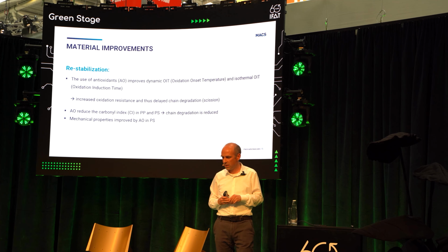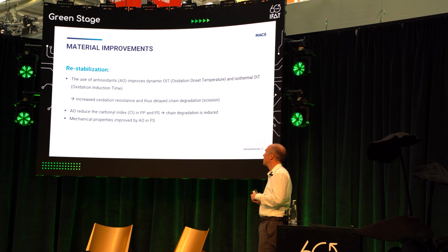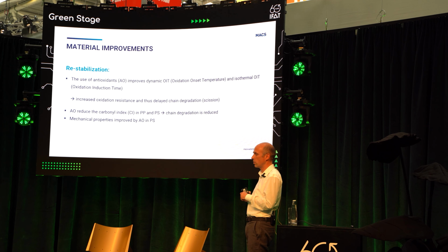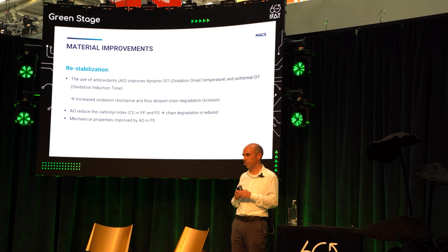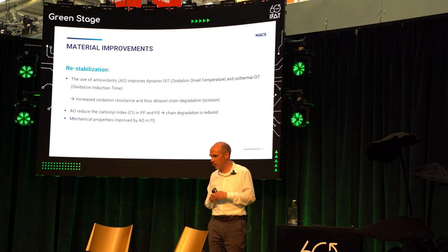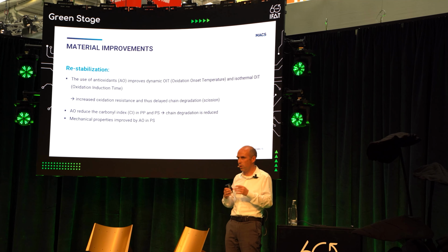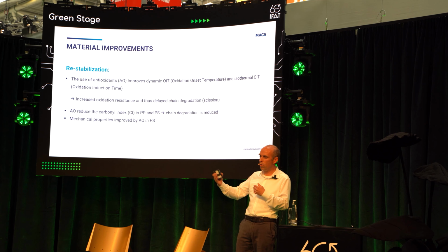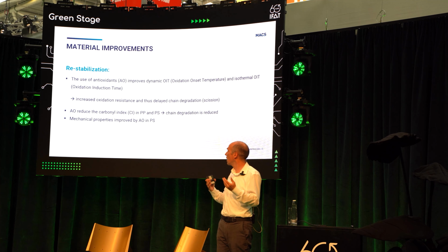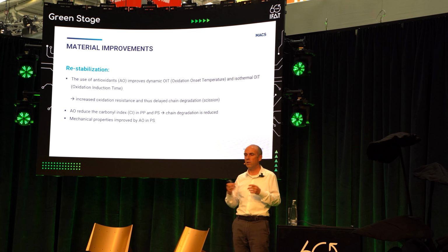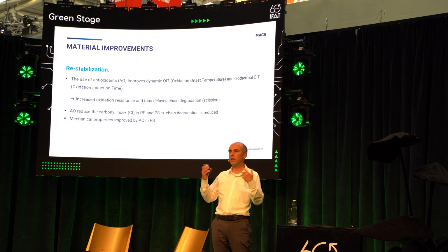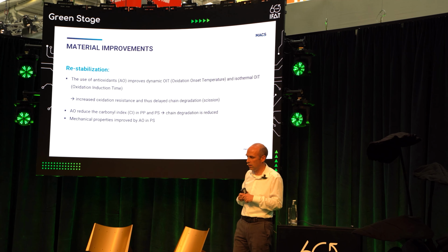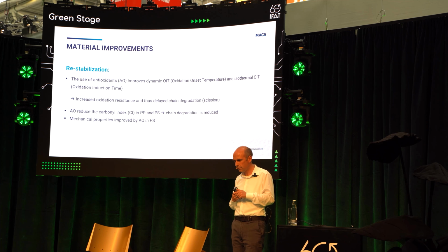How to sum this up? We could clearly see a positive effect of restabilization, and it also does not negatively affect the oxidation behavior. And the antioxidants are mainly, the name tells us this, mainly for improving the oxidation behavior, but it also improves mechanical properties. We could clearly see this in these tests. We could clearly see a lowering carbonyl index. So degradation is really delayed.